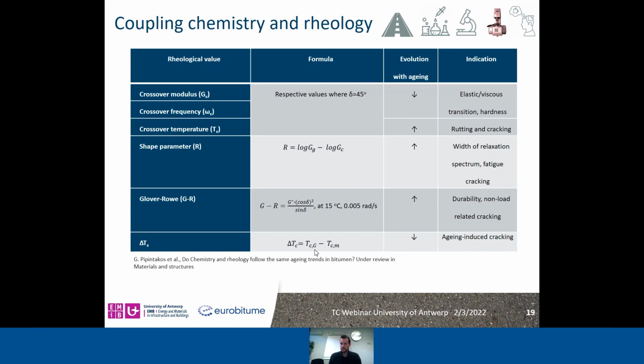In case you are interested to know more about them, of course, I would be glad to discuss them after my presentation. All these values are extracted after you construct master curves, and so you need a variety of different temperatures in frequency sweeps in order to construct the master curves, and also low temperature should be taken into account in order to extract the delta Tc value, from different geometries of parallel plates in DSR of 4, 8, and 25 millimeters.